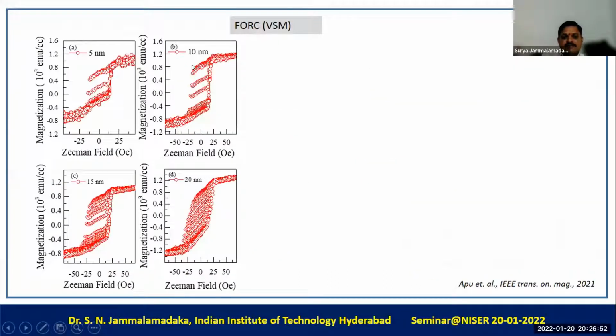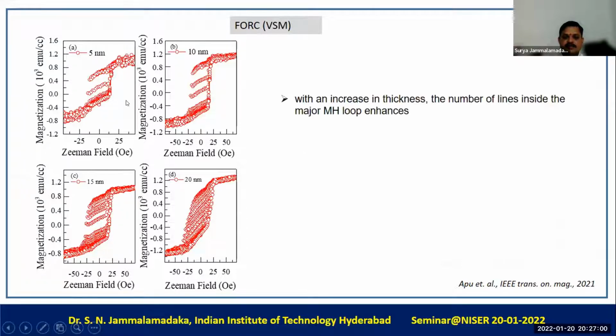These are the FORC diagrams that we have obtained for various thickness films: 5, 10, 15, and 20 nanometers. The first thing we observed is that with an increase in thickness, the number of lines inside the major MH loop increases. For 5 nanometers, we don't see many lines. For 10, a few more are there. For 15, a few more are there. And for 20, we could see many, many lines in the major MH curves.